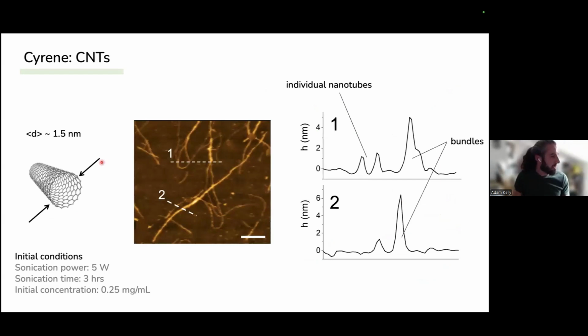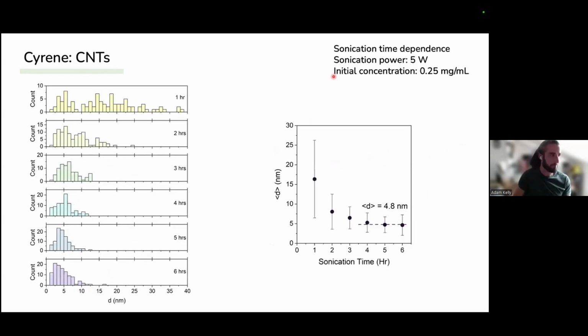So we did AFM in this dispersion, and the important thing we find here is that we are producing individual nanotubes. They're visible quite clearly from the height data, and we're also producing bundles. So even though this was just a guess at the sonication time and concentration, we do produce nanotubes, so it is possible to produce them in there. We just need to figure out the conditions under which we can maximize the amount of individual nanotubes that we can produce in Cyrene.